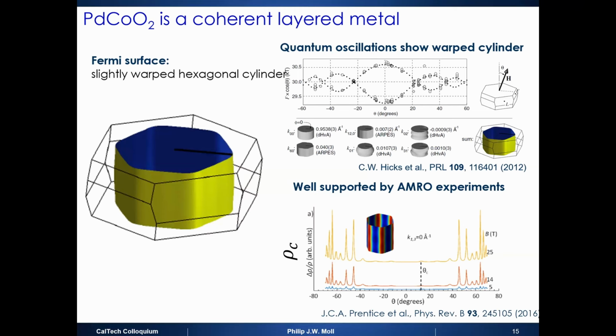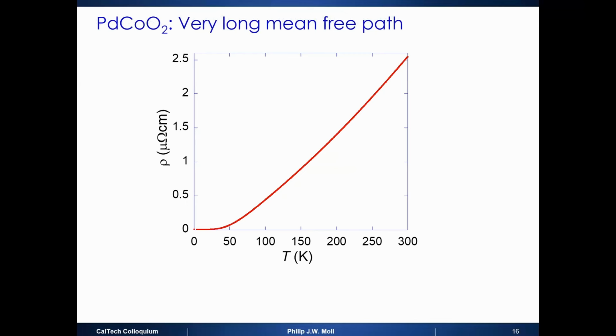There's no mystery here. This is what happens just from free electron bands on a hexagonal lattice. It's the crossover from the whole cylinder to the thing, fine-tuned to the point where it's almost exactly hexagonal. It's ultra clean. You can see all beautiful quantum oscillations in this. So we know the Fermi surface of this material very, very well. It happens to be the most conductive oxide that we have. Oxides tend to be a little bit bad on the conduction side.